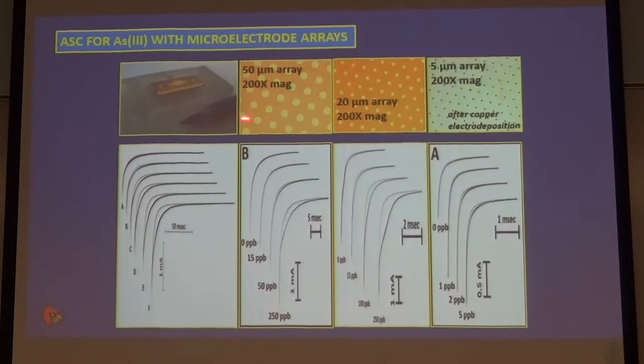Now, we have to keep those exposed areas of the electrodes close enough. This cell is about 100 microns thick, so we want to keep those within 100 microns of one another so that the diffusion time to exhaust the whole cell doesn't increase much. It's hard to see from this slide because the scales are constantly changing. That's the data I showed for those other arsenic concentrations. If we skip over to the smallest array, we're just using 5 micron holes. Now we're looking at sub 10 ppb signals. These are small, but we can still see them and measure them quite well.